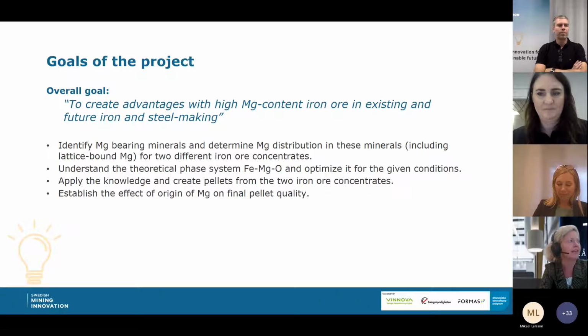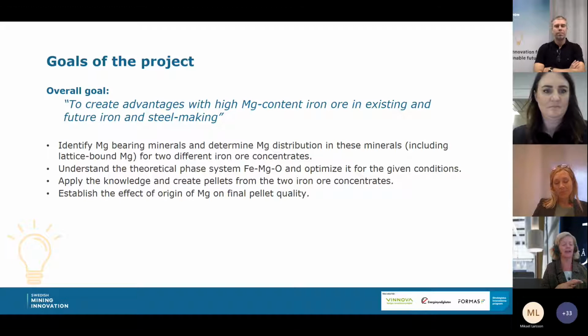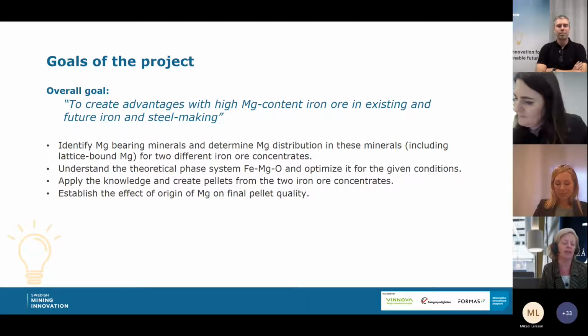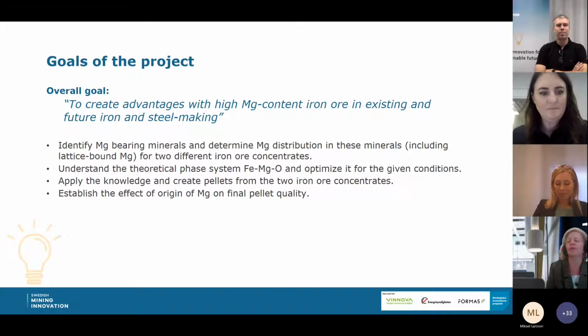The purpose is then to study the correlation between the magnesium distribution in an iron ore concentrate, so where the magnesium is present and to what extent, for two different iron ore concentrates that might have magnesium in different parts, both in the actual iron ore but also in gangue. And to understand the theoretical system of magnesium, iron and oxygen, and see what is possible to do theoretically. To apply this knowledge and create pellets from these two concentrates, and then try to correlate the origin of the magnesium to the pellet quality.